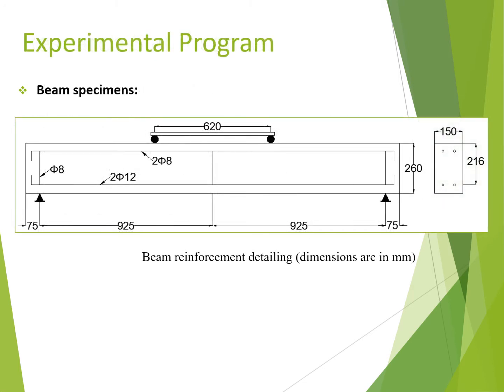As for the experimental program, the cross-sectional dimensions of the beams were 150 mm in width and 260 mm in height, and the beam spanned 2 meters in length. The beams were reinforced in flexure with 2 number 12 bars in the tension zone and 2 number 8 bars in the compression zone. In addition, the effective depth was 216 mm. You can see here from the figure that the beams did not include internal shear reinforcement except at the location of the supports and the center, to hold the flexure bars in place and to prevent premature failures at this location.